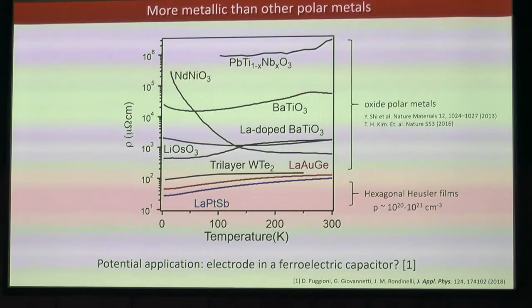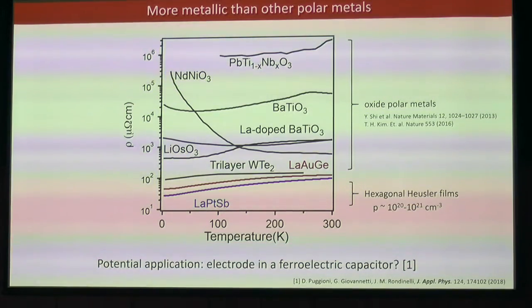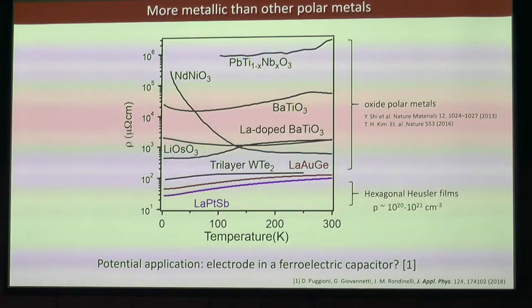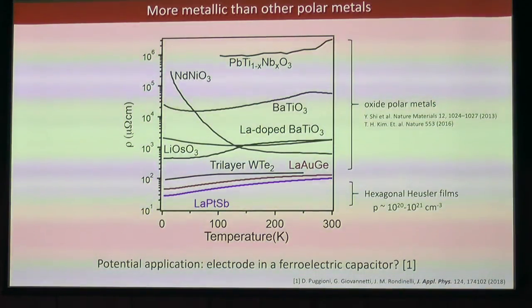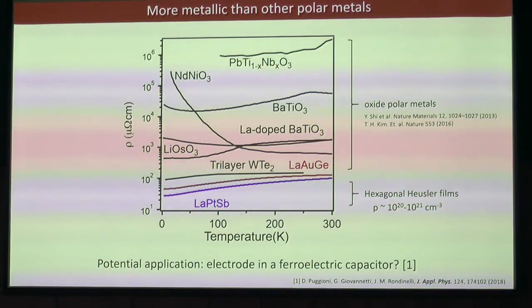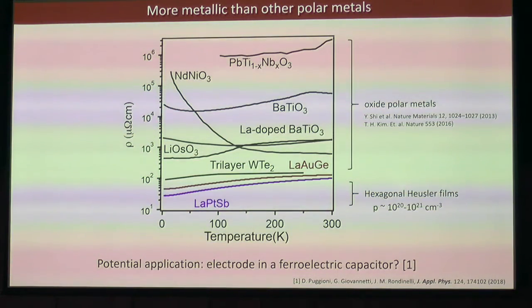One nice feature of these compounds: there's been a lot of talk about polar metals recently, with questions about why polar metals should exist. I think that's more or less been answered. I'll say there have been proposals that polar metals might be useful for applications like ferroelectric capacitors, where you make the top electrode a polar metal, and this can help solve some of the critical thickness limitations. This is based on some work by Jim Rondinelli. One problem is that most polar metals studied so far are not terribly great conductors. These materials happen to be reasonably good conductors in comparison to most oxides. So we think that might be a reason for further study here,